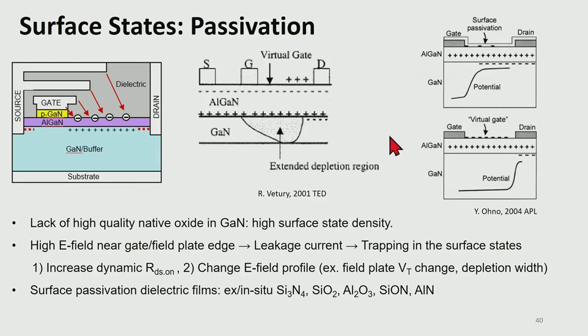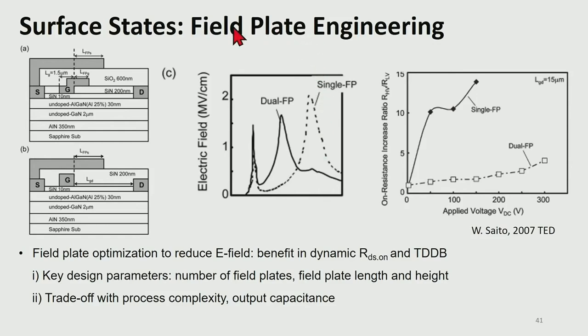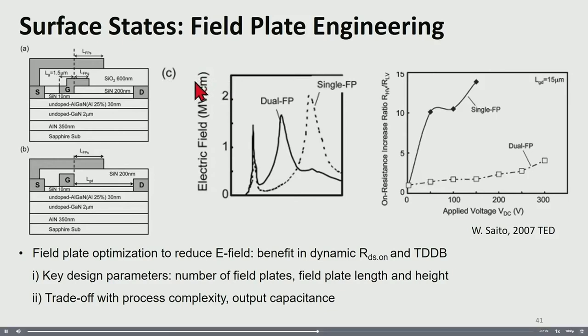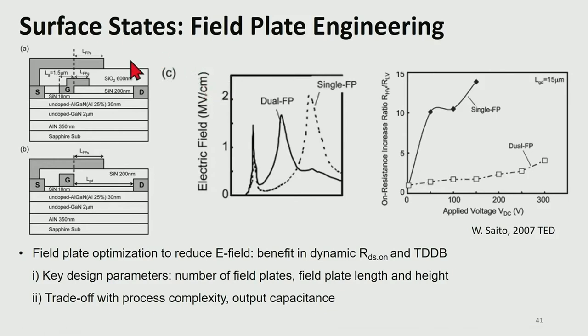So there have been various studies on diverse dielectric films, such as silicon nitride, silicon oxide, aluminum oxide, aluminum nitride, etc. But in current industries, silicon nitride or silicon oxide are mainly used to suppress this surface electron trapping mechanism. Another way to suppress this surface trapping is to reduce the electron supply. As you reviewed in the previous slide, the main source of the electrons is the leakage current caused by high electric field. So by reducing the electric field near the field plate edge, we can effectively suppress this process.